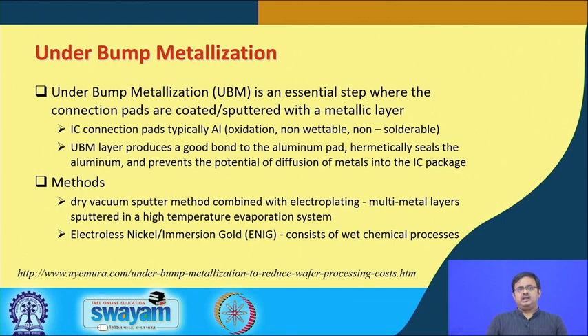So, once again, under bump metallization is the first step in bumping of the die. Bumping of the die is a two-step process. First is under bump metallization, which is like preparing the surface of the chip for formation of these solder balls. And thereafter, we do the actual bumping process. Now, why is under bump metallization required? As shown on the slide, it is to protect the aluminum which has the drawback of getting oxidized. And the other thing is, it facilitates the formation of these solder balls on top, because aluminum per se is non-wettable by solder and therefore non-solderable. So, the under bump metallization helps in both.